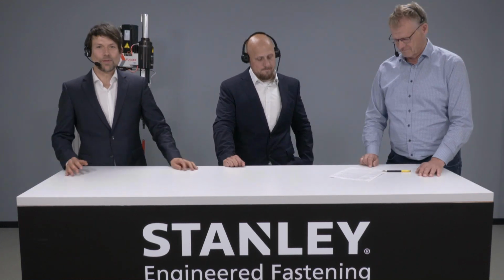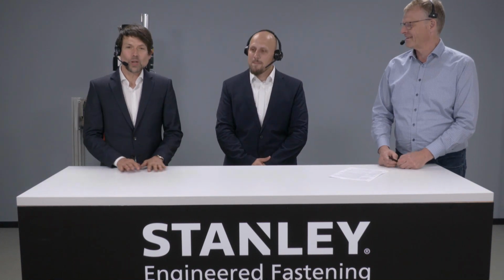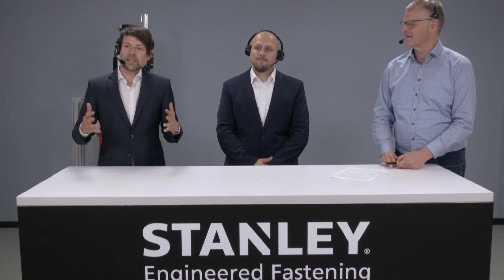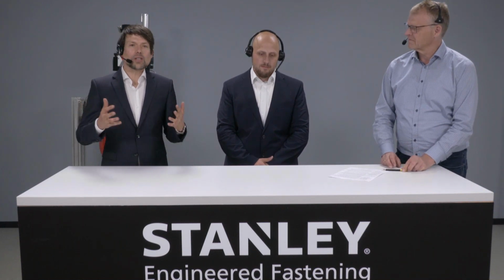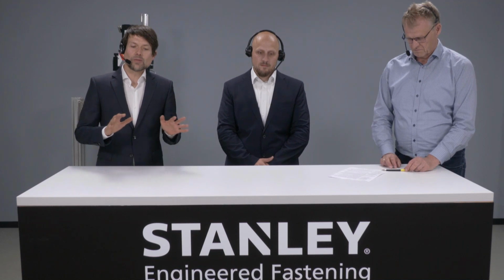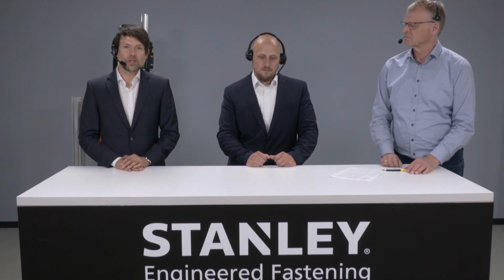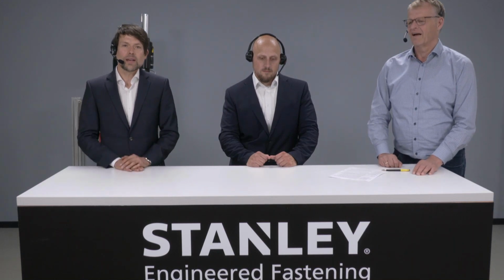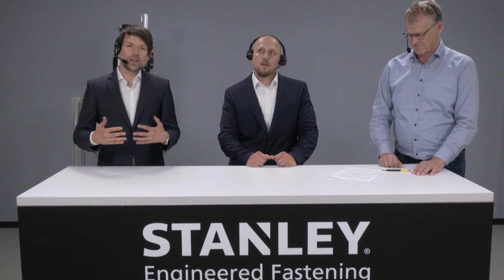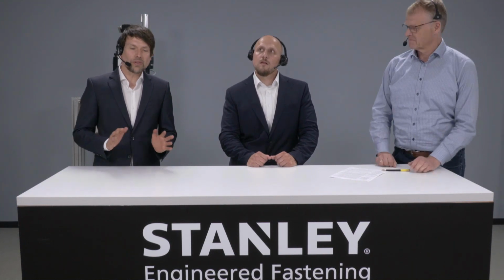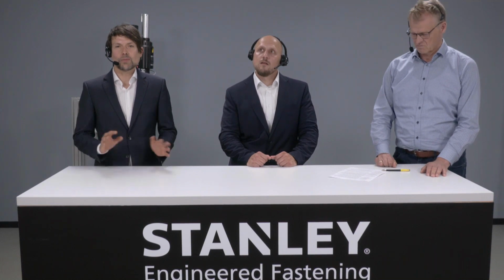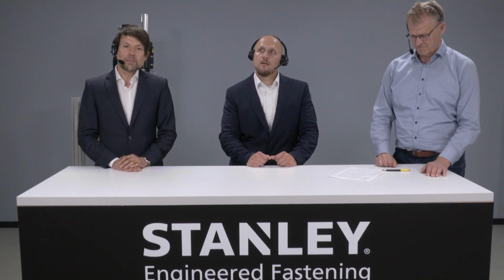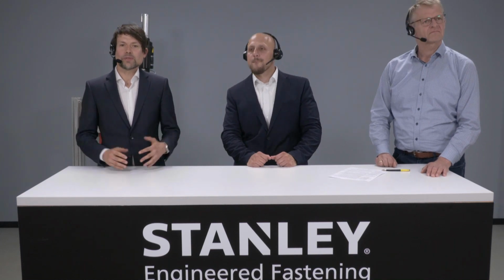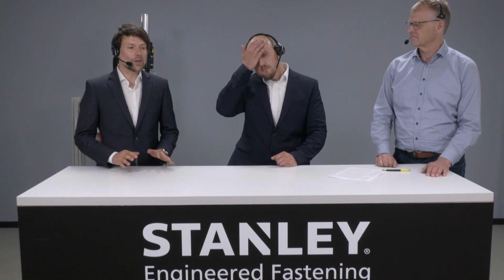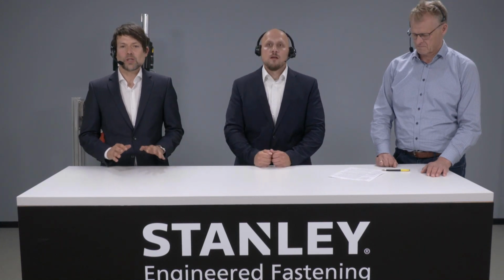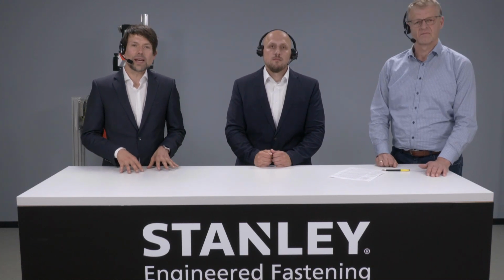Yeah. Wolfgang, let me try to answer this question. So low pressure aluminum casting. We have, let's say, a molten material such as aluminum, for instance, which we press into a cavity. And for low pressure casting, I think the maximum gas pressure you are using is 0.8 bar. So that has some implication on the casting. Usually there is a minimum thickness with these castings, about 3 millimeter. The mechanical properties, however, from what we have seen, are relatively good. The vast majority of the casting joint evaluations we are doing with high pressure die cast materials.